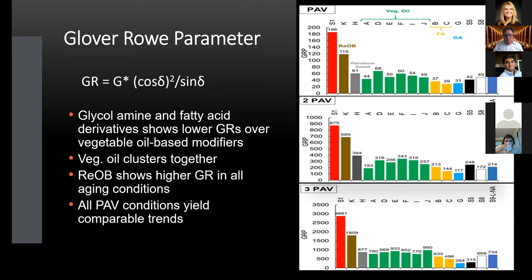The Glover-Rowe parameter is considered a useful parameter for describing cracking in many asphalt pavements, particularly for issues that are associated with durability and non-load associated cracking. As you can see by the graphics on the right-hand side of the slide, on the top is single PAV, 2 PAV, and 3 PAV as you go down the slide. If you notice, the scale is increasing and the Glover-Rowe values are increasing with aging.